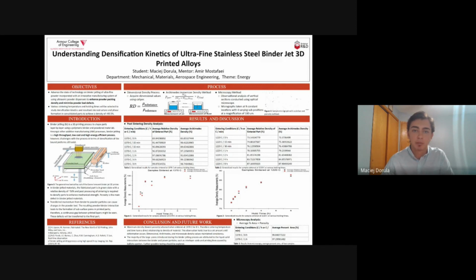Optimal process parameters were used to 3D print stainless steel 316 low carbon feedstock with an average particle size of 8 micrometers, followed by sintering. Various sintering parameters and holding times were selected to study densification kinetics and resultant microstructure and phase formation in consolidated parts to achieve a density of greater than 99.5%.